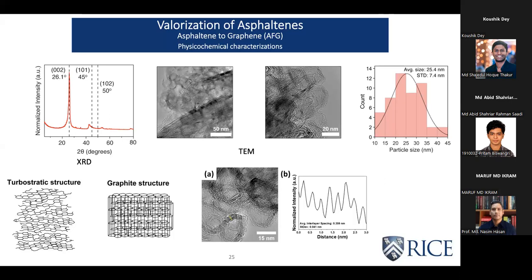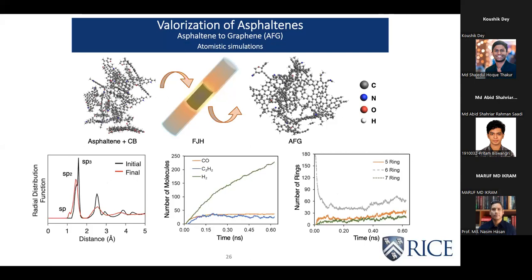Now, I know in this group many of you do molecular dynamics simulation. We also did a collaboration with the University of Washington, and they did some molecular simulations. So basically, they took one of the asphaltene structures, and here CB is carbon black, which was also added in experiments, because flash Joule heating is actually a resistive heating process. And for this process to work, we need the precursor material to be electrically conductive. Because asphaltene is insulative in nature, we had to add some carbon black, which gives the conductive nature.